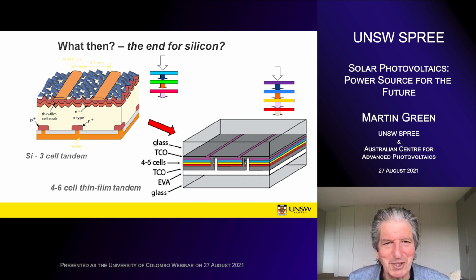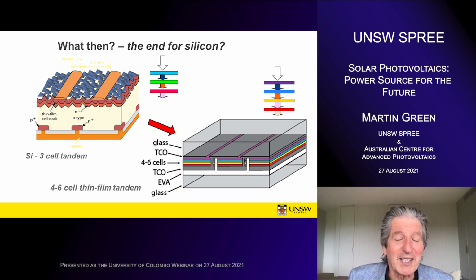You can keep repeating that procedure and eventually double the efficiency of a silicon cell by stacking sufficient cells on top of it. But each time you stack a cell on silicon, the number of photons it's got to work with reduces to the fraction determined by the number of cells in the stack. So the contribution of the silicon cell becomes less and less. With 2 cells stacked on top of it, the silicon cell is only giving a third of the power contribution that it would if it was by itself. So it's becoming less important to the whole procedure. And by that stage, the materials that you're stacking on silicon would be similarly well validated as compared to what silicon is now. So manufacturers would be starting to get a lot of confidence in them.